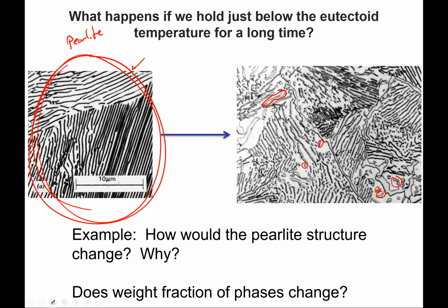Now note that when we do this, the weight fraction of the phases is not changing. So we're not increasing the amount of the cementite or the ferrite. We're simply changing it from layers into spheres. The weight fraction comes from the analysis of the phase diagram. That's the equilibrium values that we are looking for in terms of the phase fractions.